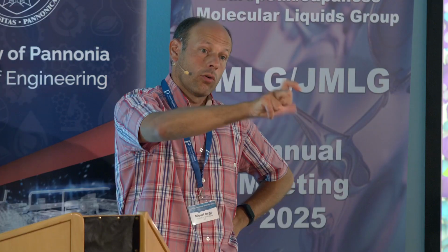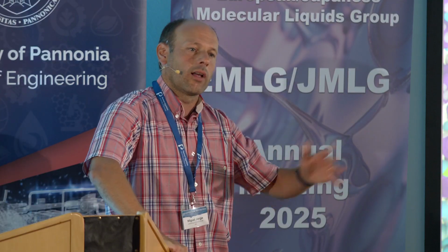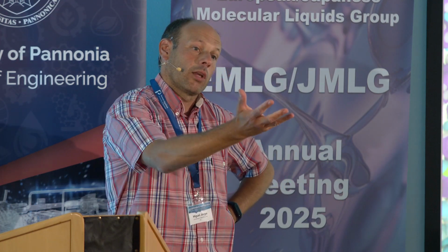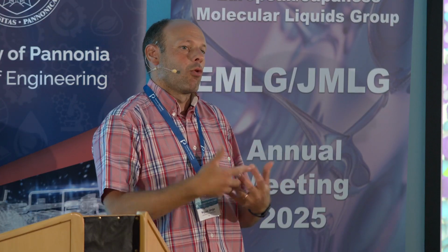You could do that, right? We thought about doing that. You could do that, for example, with a kind of hybrid MD Monte Carlo step, and that's possible to do. But then we tried to go to the reactive way instead of doing that. That would probably be a bit more realistic. So the problem, of course, is that you really don't have information about the chemical potential of these species. So you cannot really develop a robust acceptance trial for removing or replacing a dimer with a monomer, right? Yeah, you can guess, but it's not going to be very realistic.